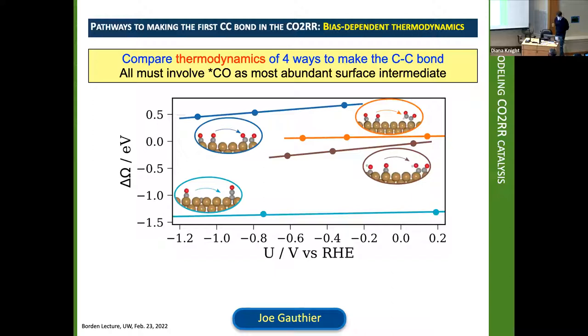And this is then a summary of the bias-dependent thermodynamics for a bunch of pathways. Down the bottom, the blue pathway is the recombination of a surface carbide, if you like, with CO. That's the most favorable. If you are able to reduce CO all the way to surface-bound carbon, that's the most favorable pathway to make a C-C bond from the thermodynamic point of view.